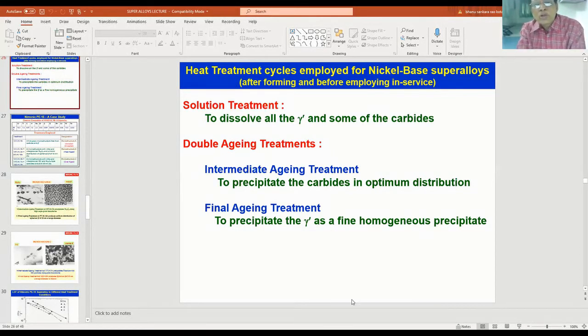Now, the different phases have to be put at different places. For that, different heat treatments have to be given. The composition is the same, but the size, the shape, and the volume fraction all depend upon your heat treatment. The grain size of the superalloy depends on the solution treatment. These heat treatment cycles are employed for nickel-based superalloys after forming and before employing them in service. That is, after fabrication of your component and before they are put in service.